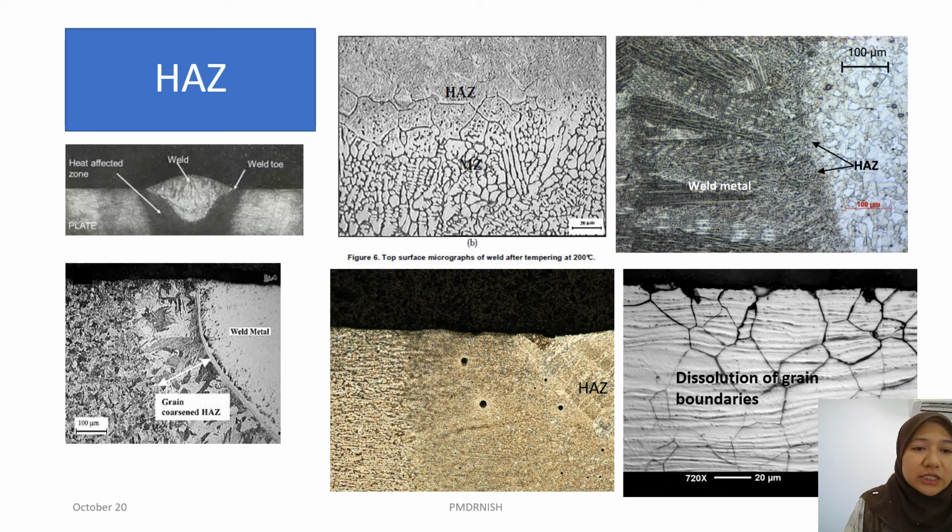The weldment is very easy to distinguish because it is in the form of a dendritic structure. And the cold work unaffected base plate is normally also easy to see in the microscope because it is in the rod structure. Okay, so this is the fusion zone, the melting zone. So this would be the heat affected zone. You can see that some has sufficient time to grow into a large grain size. However, some do not have sufficient time to grow any phase.